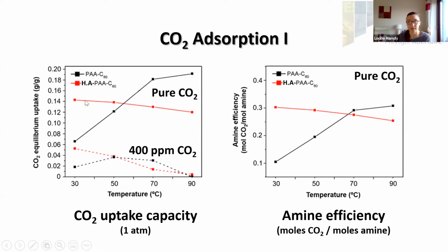The hydrophobic additive material behaves very differently. We have a far lesser temperature dependence of the adsorption, and importantly, adsorption is actually highest at the lower temperature of 30 degrees. Now, this we can see is due to the hydrophobic additive, but how does it actually influence the material such that we see the adsorption in this way? We think that the additive, being hydrophobic, repels the amines, the polymer chains, and creates diffusion pathways through repulsion, allowing the CO2 to access the amines.